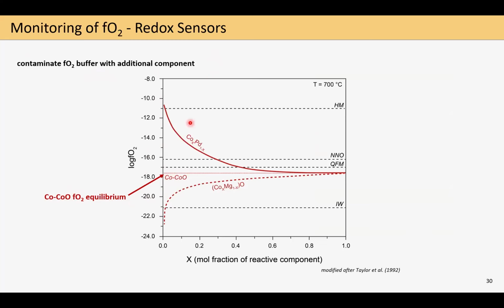When we add, for example, palladium metal or magnesium oxide to this buffer equilibrium, so we contaminate it, these additional components will react with the buffer assemblage to form either an alloy or a solid solution, where the composition of these two new compounds will be directly related to the imposed fO2 conditions. So if we measure the composition of such a cobalt-palladium alloy, we can back-calculate the fO2 conditions at which it formed. In this plot, you see that the cobalt-palladium system more or less covers the entire fO2 range most important for magmatic processes, meaning that we are currently using this system to monitor the fO2 conditions in our vessels.